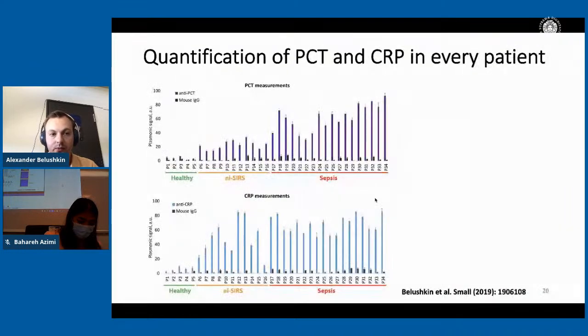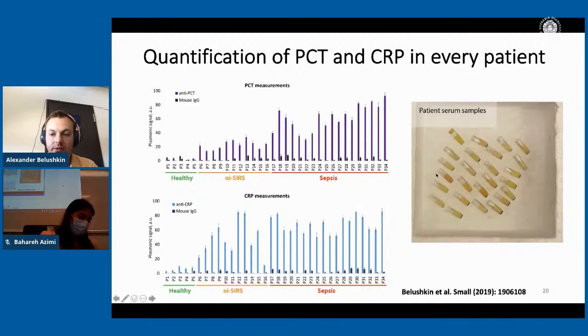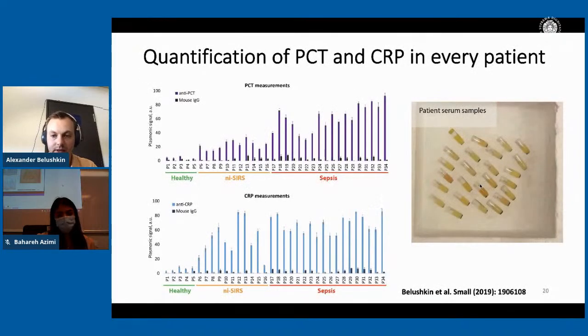So having that, we moved on and quantified all of the 34 serum samples that we had for both PCT and CRP. As you can already see here, PCT seems to be a more discriminative predictor between the 3 groups, while CRP is non-specifically elevated for inflammation, but it's very hard to tell whether it's of infectious nature or not. At the same time, although the serum samples had pretty different optical properties, like different turbidity, different color, different consistency, the results were very consistent, again showing the robustness of our system.